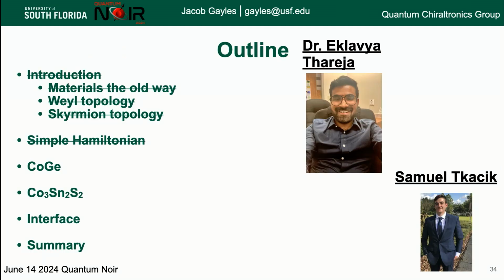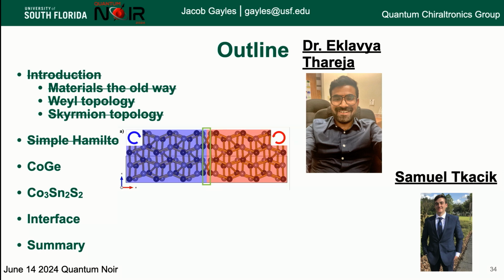Good. All right, the last one. The last one, sorry, there should be some crosses here. We're working, now we want to go to the interface, yeah? And this is a particular type of interface where essentially because these materials are chiral, we want to just switch the chirality on this interface. So it's just a crystal domain. It sounds pretty simple, something that you don't want, but we get very interesting properties come out. And the reason why that follows cobalt tin sulfide, this is the discrete limit of that very long wavelength spin spiral.